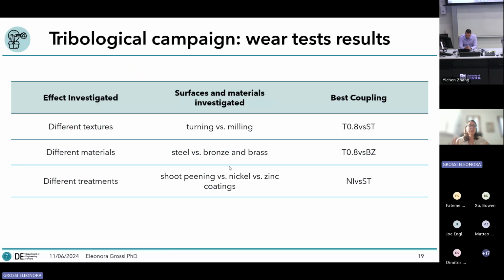When investigating the effects of different textures, I focused mainly on turning and milling, and I observed that the best performance is reached with the turn disc with the smallest roughness values, which in this case is 0.8 micrometers. So I selected this disc as the reference for the following test.